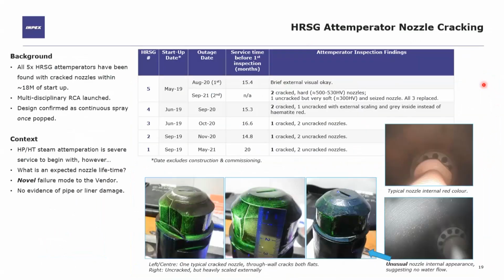Right, so we've been confronted by finding at least one cracked attemperator nozzle in all 5 of our HRSGs during their first inspections, which was around 15 to 18 months from startup. And there's a lot of work. I know I've heard along the grapevine that there's a lot of work that goes into attemperators. But is this normal? Should we expect a minimum of 2 years from a good attemperator, or 4 years, or perhaps more?